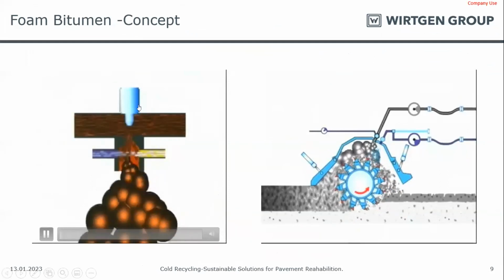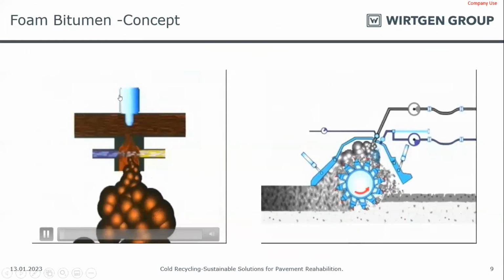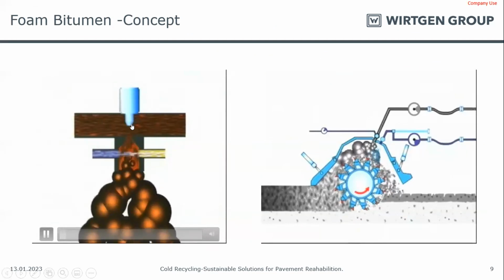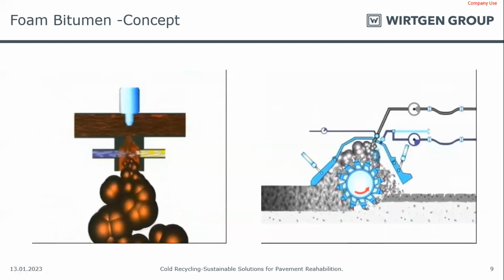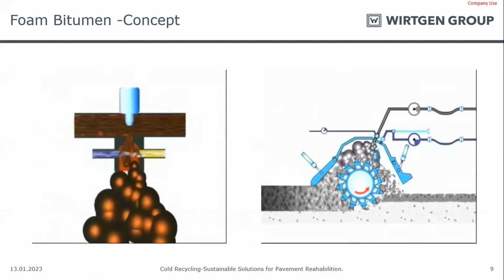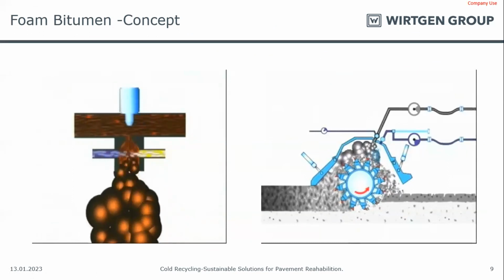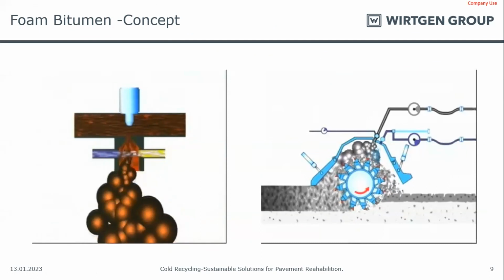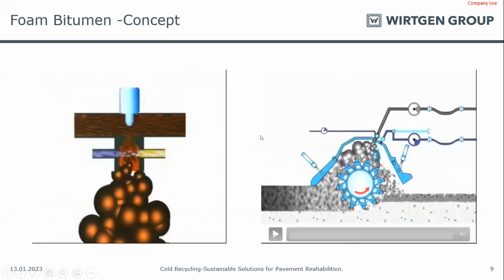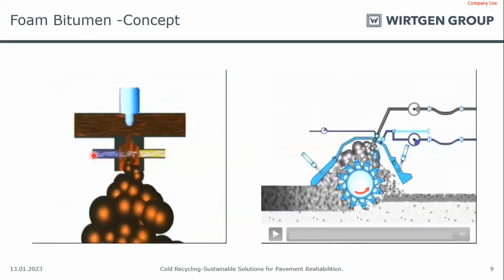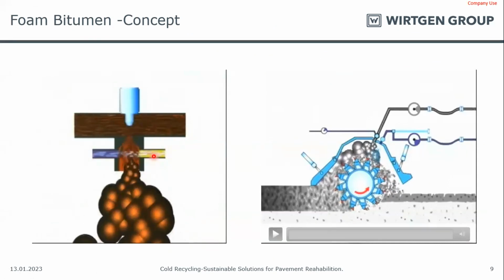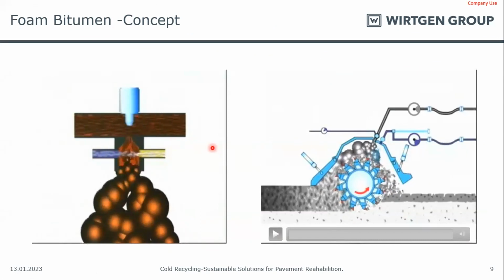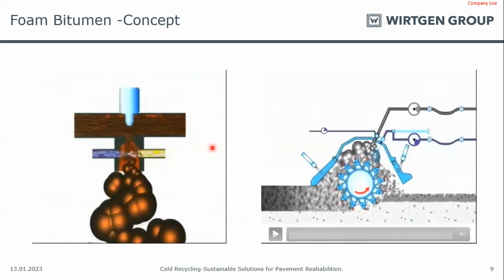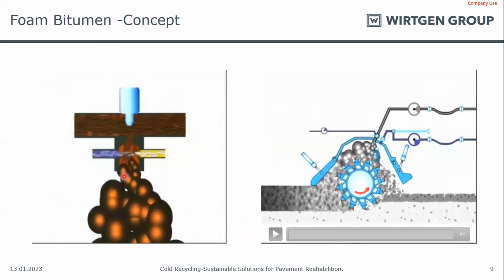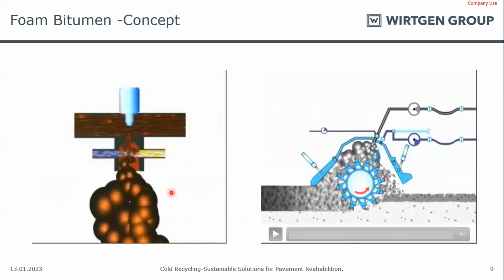This is the foam bitumen concept. On the left hand side, you can see the nozzle for the hot bitumen. The bitumen is heated to a temperature of 160 to 180 degrees Celsius, and we generally use VG30 grade. When the hot bitumen comes in contact with water from the water line as well as compressed air, it expands 18 to 20 times its original volume. It creates foaming of bitumen, and this foam bitumen covers the entire surface area of the aggregate.